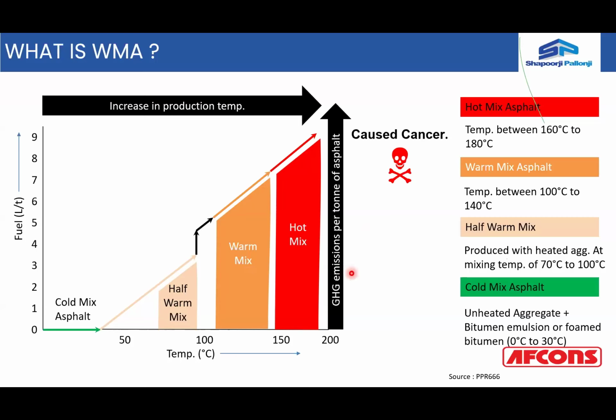So the crux of this discussion is, if you are adding an additive which is supposed to control the mix temperature, and you are not controlling the mix temperature, because there are other advantages for that particular mix, like increased moisture resistivity. But if you're only focused on moisture resistivity, and by adding an additive you're not controlling the mix temperature, you will end up with poor riding quality. So those things we will touch upon slowly. Now the